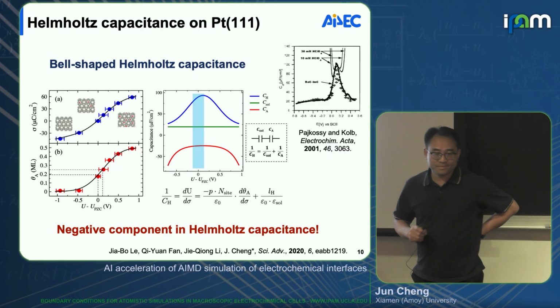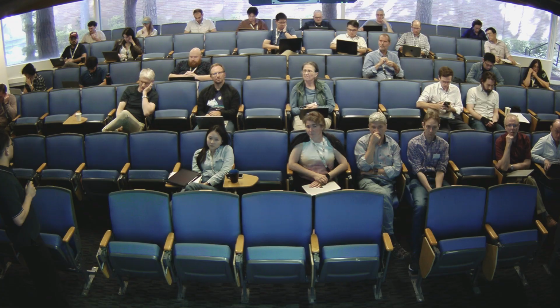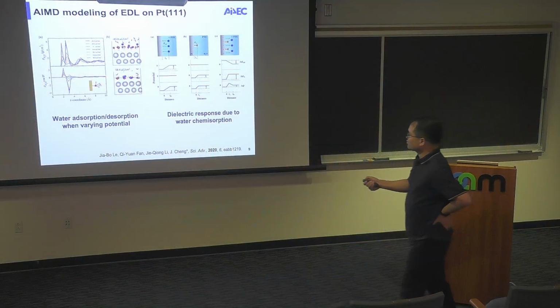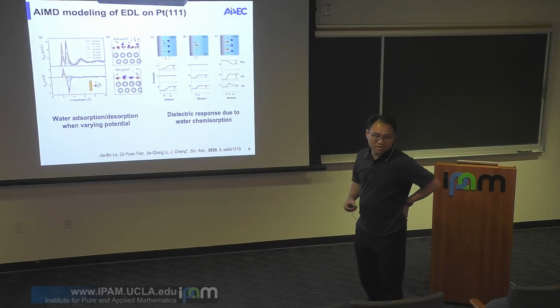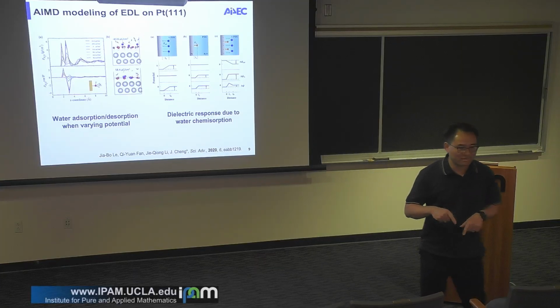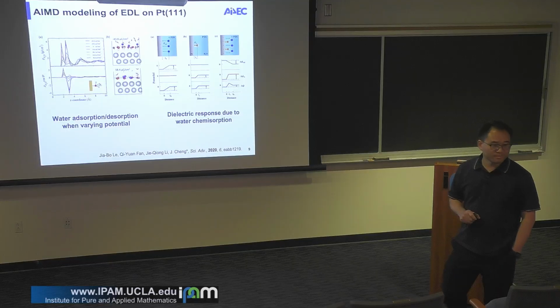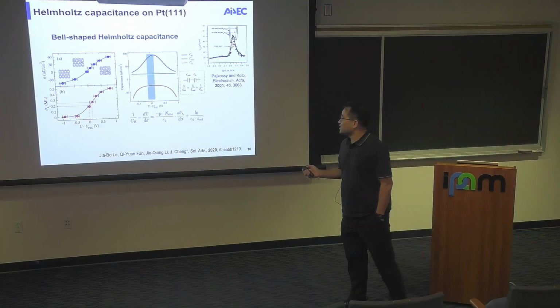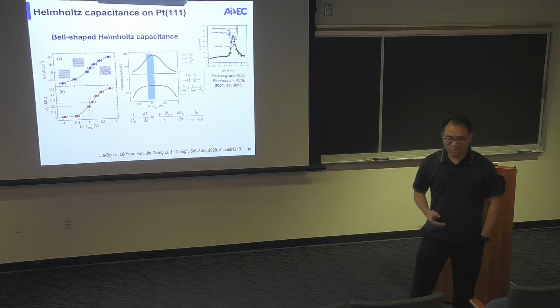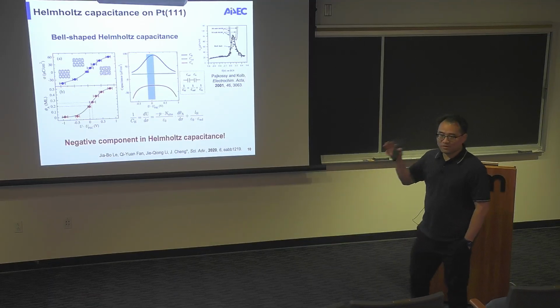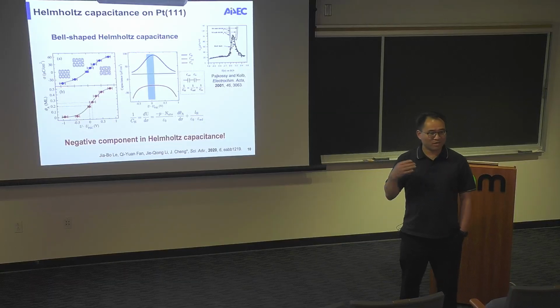Question. So what do you have adsorbed over this whole potential range between minus 0.5 and plus 0.5? Is it all about water molecules, or? It's chemisorbed water. Okay. The chemisorbed water are referring to the first peak, right, where you have the oxygen pointing down, directly connected to the platinum. But then at minus 0.5, you already are in the hydrogen chemisorption region. Yeah, that's actually a good point. Is that the same reason I asked you the question in the morning? In this model, we don't have any specific adsorption of hydrogen and OH.